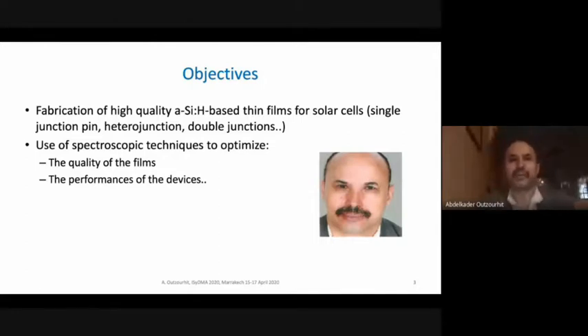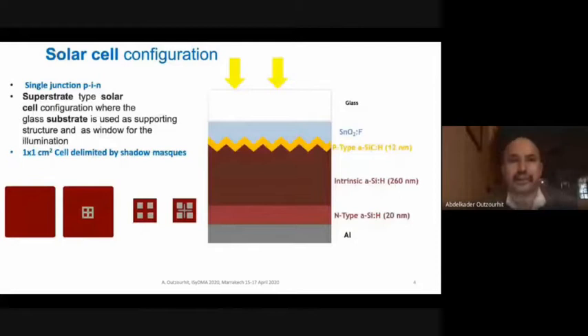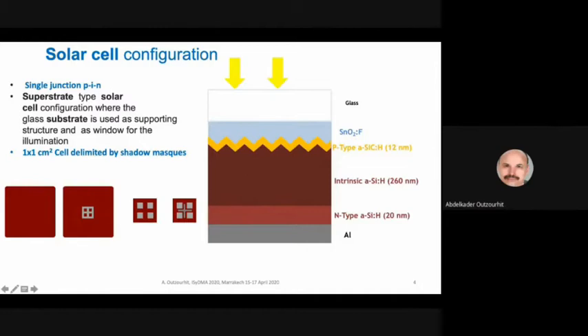Okay, so the solar cell configuration that was developed is a single junction PIN type solar cell. It's in the superstrate type configuration, where the glass substrate is used as a supporting structure of the cell, as well as a window for illumination of the cell. So the cell is basically composed of an FTO coated glass substrate on which a P-type hydrogenated amorphous silicon carbide thin film was deposited with a thickness of about 12 nanometers.